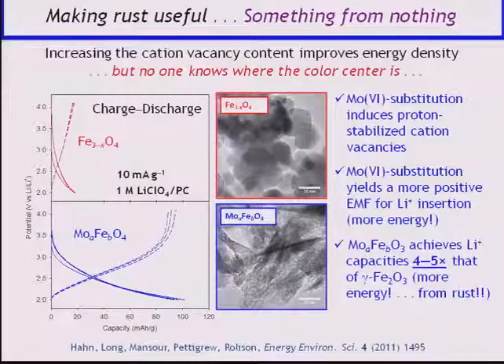But we don't know where the color center is. People know that all of these insertion oxides are electrochromic. They're usually very ugly electrochromic materials. But that's telling you something about the electronic state of the metal centers as it's charging and discharging these lithium ions. When you have anion vacancies, such as in vanadium, you often see a shift towards the near IR, but nobody has been willing to calculate for us where the color center would be for the insertion metal near a cation vacancy. So we're just going to have to go look for it ourselves.